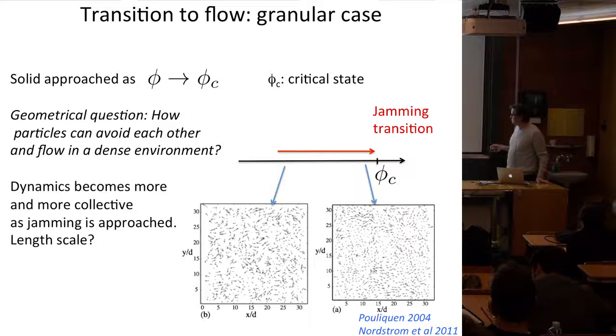In those pictures, you remove the mean velocity and you just look at the fluctuations of velocity. And what you find is that if the slope is high and you go fast and it's dilute, essentially the fluctuations of velocities are very small. But as you approach this point, suddenly the dynamics starts to become very collective. So when it's too dense, particles cannot decide on their own where they want to go. They need to coordinate, if you want. So you see some kind of big eddies that appear in the flow. And so one question is, what is this length scale? What governs it?